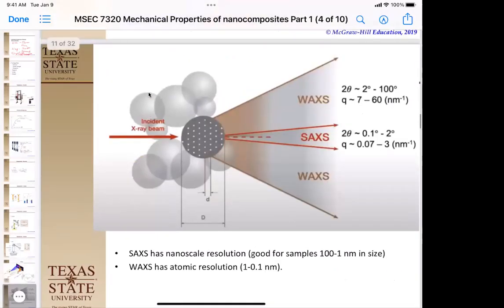So if we think about it, the small angle X-ray scattering tells us things in the nanometer range. So we can actually start looking at whether our nanoparticle is crystalline or not. If our nanoparticle isn't crystalline, we're going to see a wide, broad absorption because of the scatter. If it is crystalline, we're going to start to see where the planes might be.